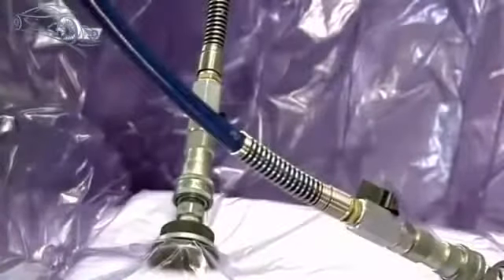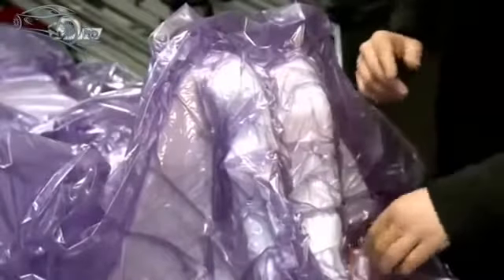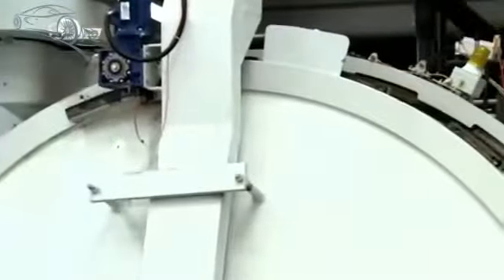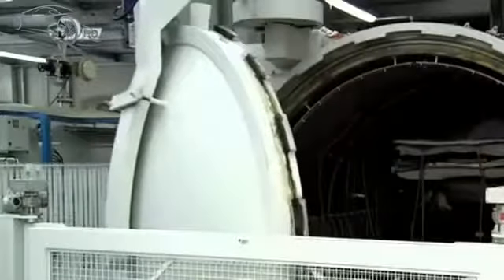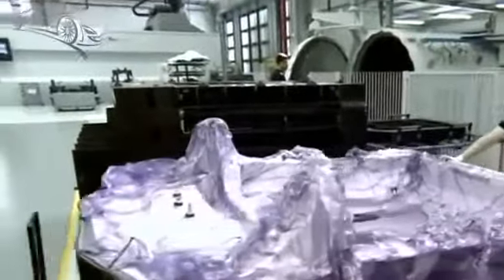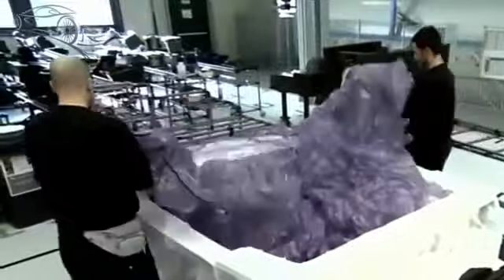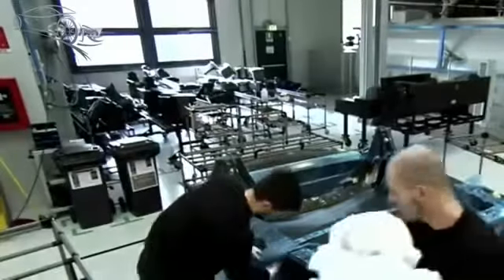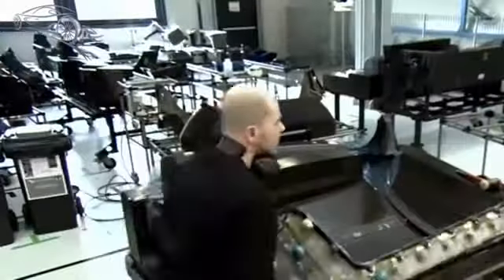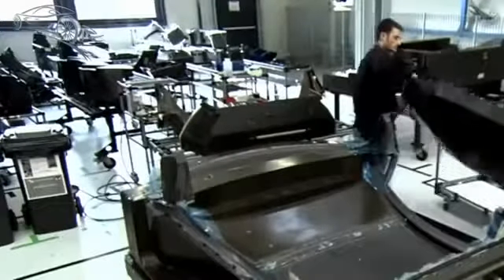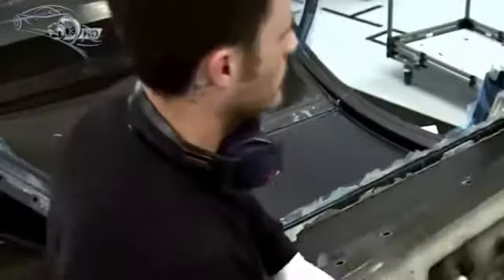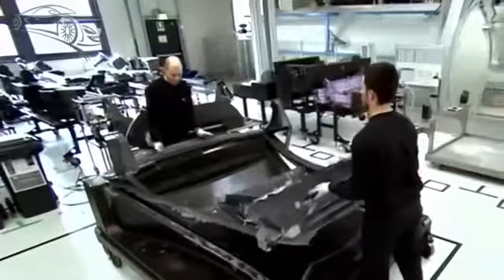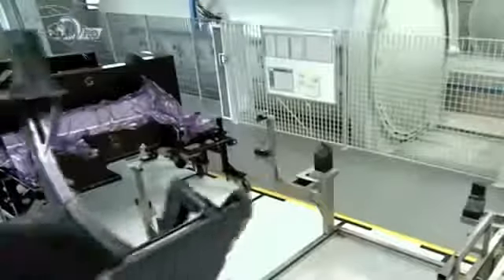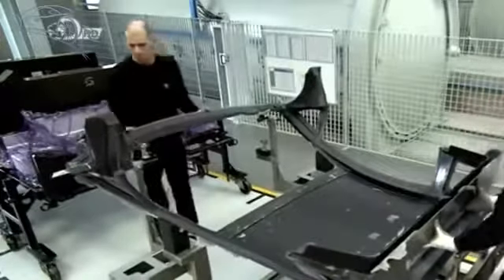The air is then removed, resulting in atmospheric pressure forcing the layers of carbon fiber to shape to the mold. The mold then cures in an autoclave at a temperature of 135 degrees Celsius. During this process, the carbon fiber releases the impregnated resin into all areas of the fabric. The vacuum bag and protective white cloth are removed to reveal the solidified carbon fiber part of the monocoque. The mold is then disassembled to allow for the easy removal of the part, in this case, the roof section. It's then transferred onto a work cart, where any excess resin is removed.